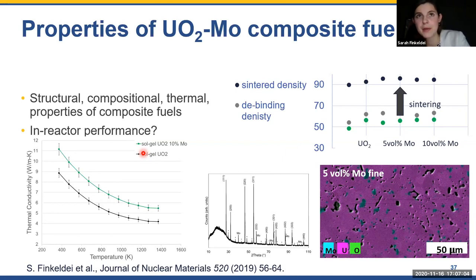It was already observed by another group a few years ago, and they mentioned that the porosity in a sol gel derived pellet is much more homogeneous than when you start from a powder. But in the publication from this group, there is no evidence that this was actually causing the increase in thermal conductivity. So we are still trying to understand this at the moment, but we're able to exclude that the density of the pellets that we measured was causing the difference in the thermal conductivity, because we corrected for those.